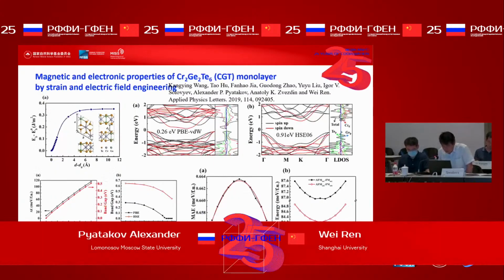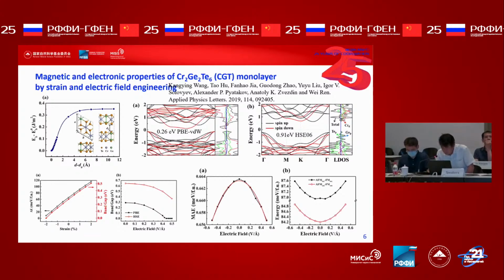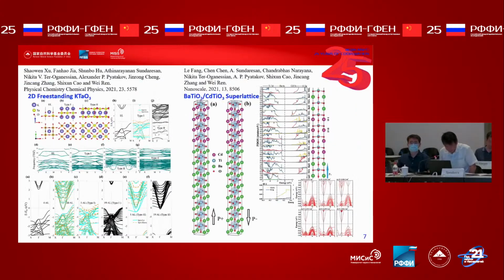We performed a detailed theoretical analysis of structural, electronic, and magnetic properties of the monolayer ferromagnetic semiconductor CGT. The moderate cleavage energy suggests that it can be exfoliated from bulk or multi-layer systems. The ground state is ferromagnetic, having 3 μB per chromium atom with an in-plane spin polarization. And the calculated band gaps are reported using different functionals. In addition, strain engineering and the electrical field might be applied to control electronic and magnetic behaviors of such a CGT monolayer.